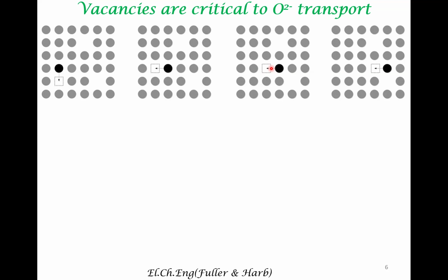So this is pretty much like what happens in a semiconductor. When you say a hole is getting transported in a particular direction, what is happening is electron is actually getting transported in the opposite direction. So electron transport is inherently coupled to hole transport. Likewise, an oxygen anion transport is inherently connected to an oxygen vacancy transport.